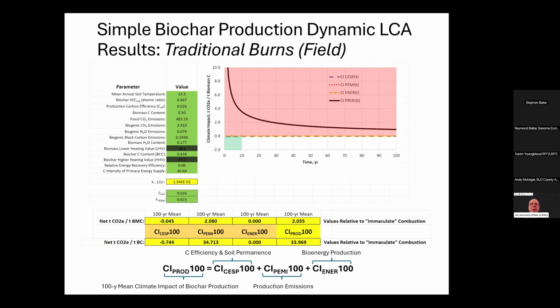It's almost identical to the production emissions, which is the dotted red dots. You can barely see them behind the black line. Otherwise, with this particular burn, there's hardly any biochar created. There's no offset down below that would account for carbon efficiency and soil permanence, and there's no bioenergy. So basically the one thing we're measuring in this particular case is the production emissions.